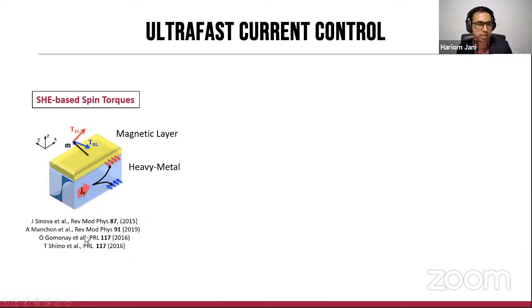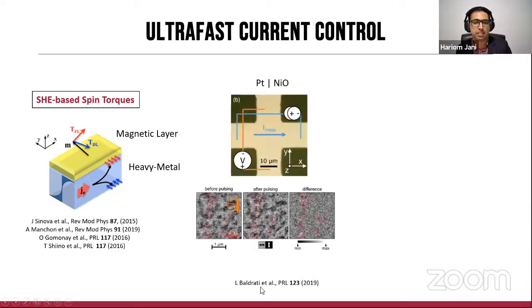Very excellent reviews have been written on the subject, particularly by Hariom and his colleagues, and also how this can be used to drive antiferromagnetic order. There are some very interesting results here. Firstly, of course, this was demonstrated in platinum nickel oxide, where the heavy metal is then used to inject some form of spin currents into the system. And they were able to observe the changing of the local order.